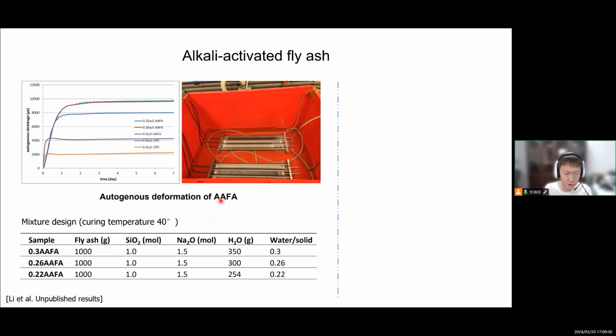So I tested the autogenous shrinkage of this system, but in water, because we normally need an elevated temperature for alkali-activated fly ash, so I used 40 degrees. We can see in the beginning there is a chemical shrinkage, and then a small expansion, very small, just a trend, and then shrinkage again. So it also has 3 stages of deformation, just the expansion is not that big.